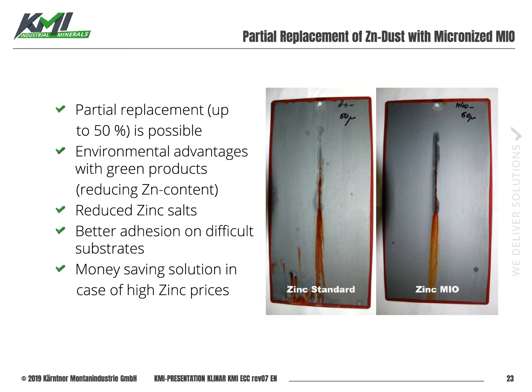And last but not least, it's a money-saving solution in cases of high zinc prices, because micaceous iron oxide is a typical industrial mineral product, traded as an industrial mineral product, which means the pricing is more or less constant with small adjustments more or less to the inflation rates. And on the other hand, zinc dust is traded on a metal exchange and the pricing is much more volatile compared to micaceous iron oxide. So especially in case of high zinc prices, it's a good alternative to use micaceous iron oxide.